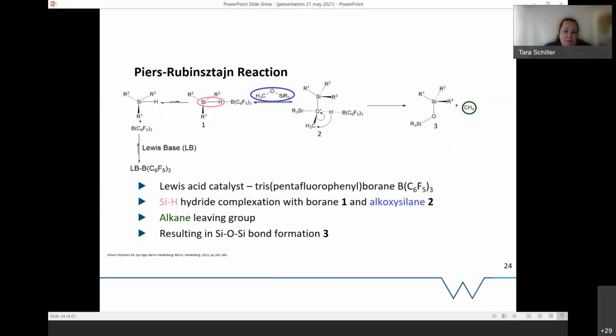So we've got a material that basically has a small amount of the Lewis base left behind. Yes, there's still toxicity issues, but in, I guess, low concentrations, there shouldn't be an issue with this. But when we look at the reaction, the beautiful thing about this is it all can be done at room temperature, and it's extremely quick as well. So we're talking, depending on the amount of catalyst, from under a minute up to a couple of hours, and it's done. Whereas a lot of the platinum palladium reactions are markedly longer.